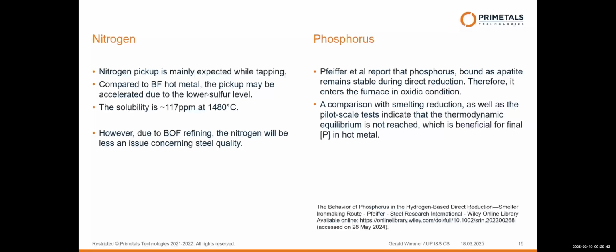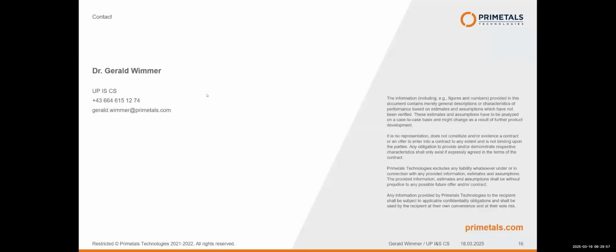And we can decide the level of carbon, silicon level similar to blast furnace, sulfur level lower than blast furnace, nitrogen level and phosphorus level similar to blast furnace. If there are any questions, I'm happy to answer them.